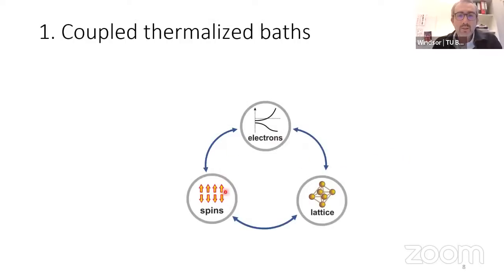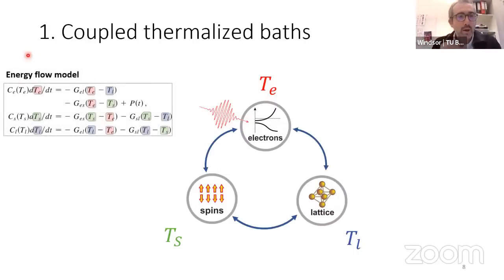So if you imagine these three kinds of heat baths or degrees of freedom, which we can assign to a given system, we can then imagine that we dump energy into the system very fast using a fast laser pulse, and the energy will flow between these degrees of freedom in a way that we can then describe using a single number for each one of these. This would be in units of temperature or energy. And we could imagine how these temperatures change using some kind of energy flow model as shown here.